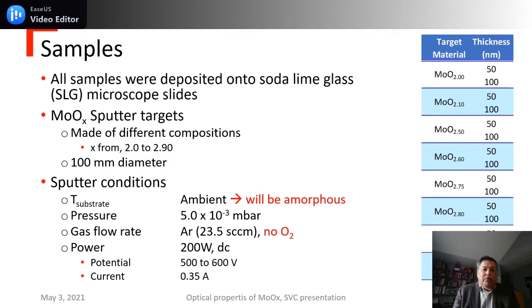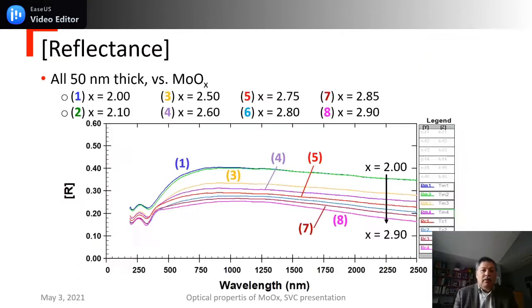All these samples were made under ambient temperature conditions, and therefore they will be amorphous, and absolutely no oxygen flow is in the sputtering, only argon. So the stoichiometry is solely dependent upon the target material. We first begin with showing you the reflectance of these samples.